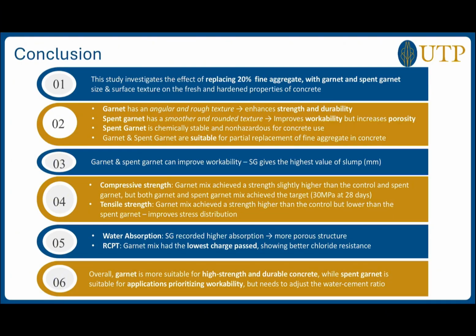To fulfill objective number 2, the slump test result has shown that garnet and spent garnet can improve workability, with spent garnet giving the highest slump value, which is 80 mm. And to fulfill objective number 3, compressive strength has shown that the garnet mix achieves a strength slightly higher than the control and spent garnet, but both garnet and spent garnet mixes achieve the target 30 MPa at 28 days. And for tensile strength, the garnet mix achieves a strength higher than the control but lower than the spent garnet because the smoother surface can improve stress distribution, which allows slight deformation before failure.